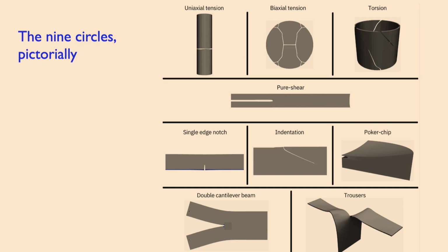So I missed the second part, but let me address the first part, right? Of course you're correct that real materials aren't perfectly incompressible. There's always a little bit of compressibility there, right? And all the developments here started with trying to explain experiments on real materials that were nearly incompressible. So even though the incompressible limit makes the point, the nearly incompressible materials are just as problematic. What you find is that energetic methods vastly overpredict the hydrostatic strength of even nearly incompressible materials.